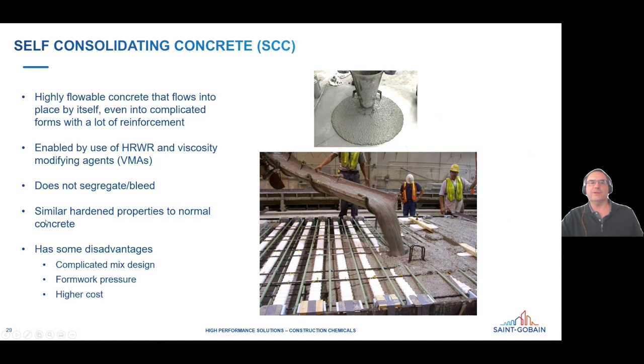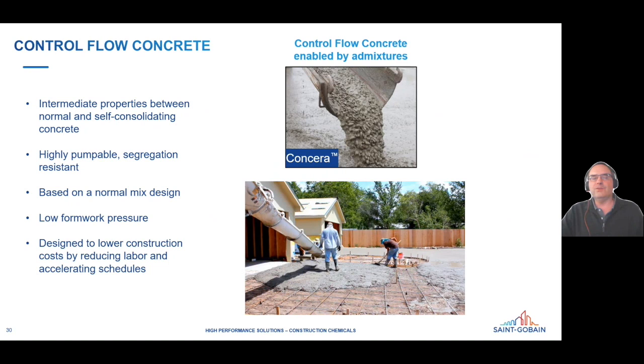There are a few disadvantages. The mix designs for this are a little more complicated. Because it flows so easily, it creates a lot of hydrostatic pressure inside the formwork. So sometimes the formwork needs to be a little bit more sturdy, and they can be more expensive. So an even more recent development is something called controlled flow concrete. And this has intermediate properties between normal concrete and the SCC self-consolidating one. And the idea here is to keep some of the advantages of SCC, but eliminate some of the disadvantages. So it's still highly pumpable.